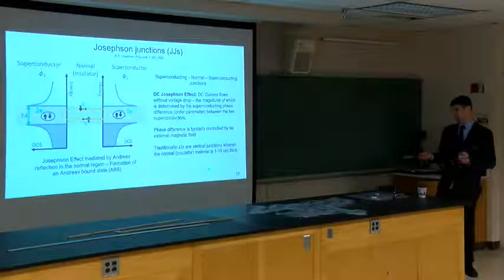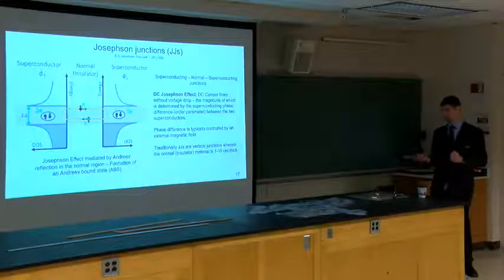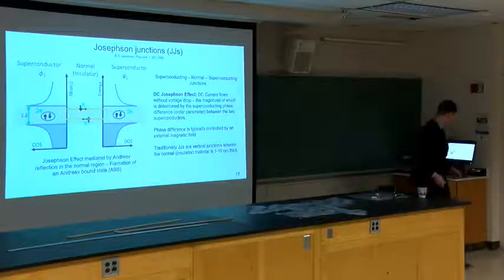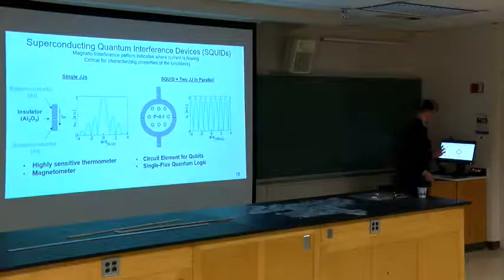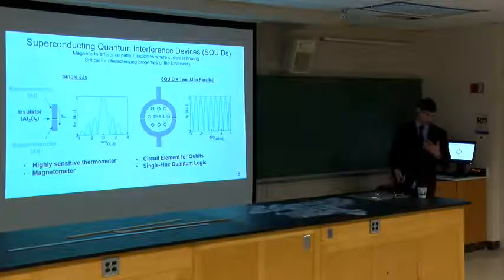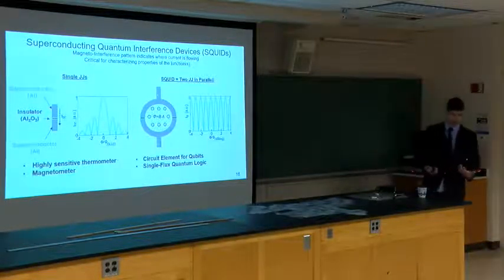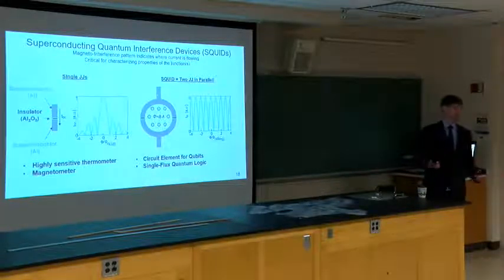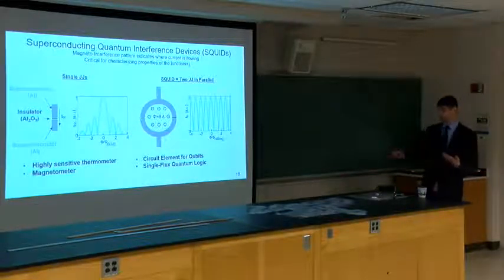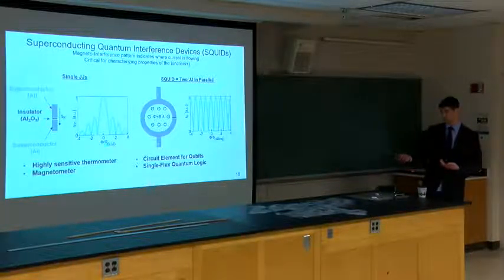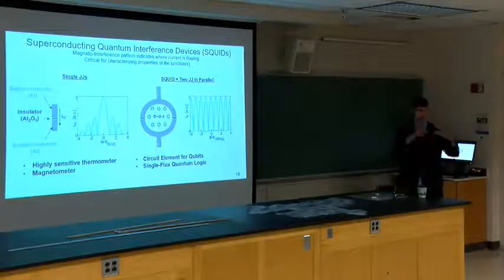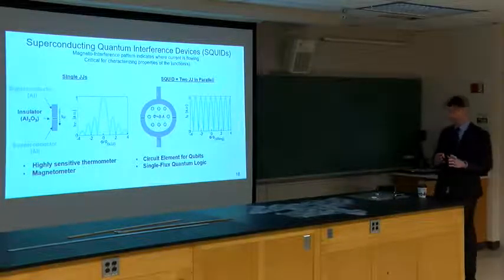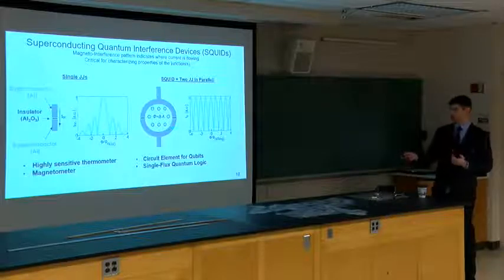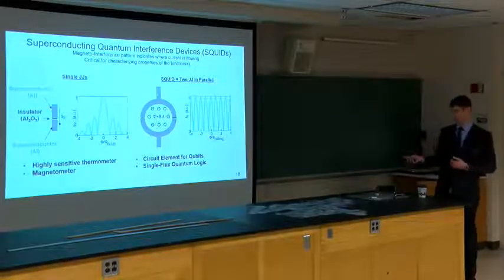So these devices are traditionally very thin insulators, so 1 to 10 nanometers thick, and they look something, on the next slide. So one of the ways that we would be able to analyze such Josephson junctions is we would put them in a magnetic field, and the magneto oscillations that show up, so this is flux as a flux quantum, so based on the size, so we have a single flux quantum in the area of the Josephson junction, is you get something that looks like a Fraunhofer pattern from optics.